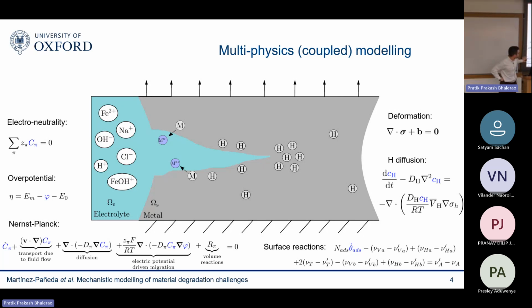And that's good, because then we can reduce assumptions and we solve the physics as they happen in reality, as a function of material parameters, diffusivity again, partial molar volume of hydrogen that we know before we run our calculation. So we don't need to recalibrate, fit things around, and we can extrapolate and interpolate between data. So this is one of the, I think, opportunities that we have in front of us.